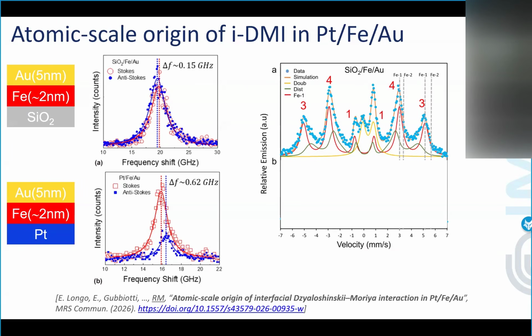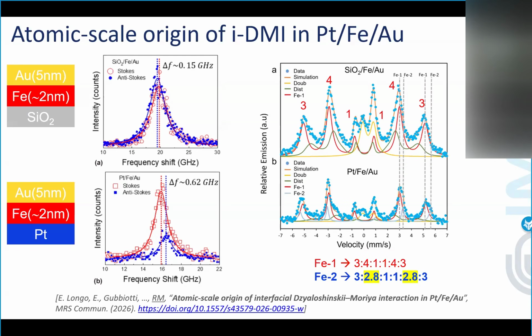And here, I say thank you again to Jean-Marc for having explained the meaning of the relative ratio between Mössbauer lines. So here we get 3-4-1 in the case of iron on top of silicon oxide, meaning that you have a fully in-plane magnetization for your iron. But something very interesting happened when we moved to the sample on top of platinum, where to interpret the data satisfactorily, I needed to introduce an additional layer, an additional iron contribution, so-called iron 2 here, where the ratio changed. So it started to be less, so 2, somehow 3 and 1, meaning that there is some non-collinearity that appears when you grow your iron on top of platinum.